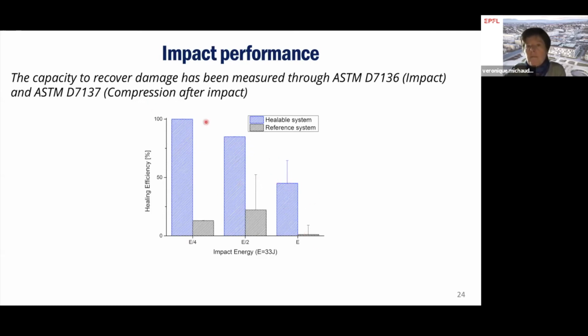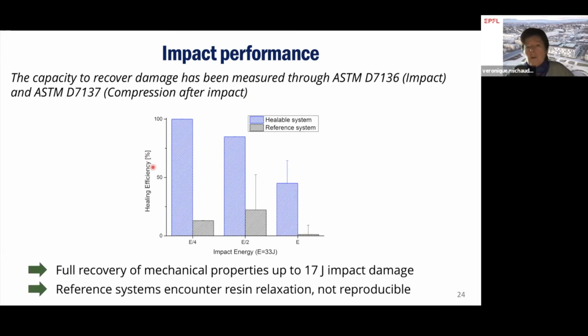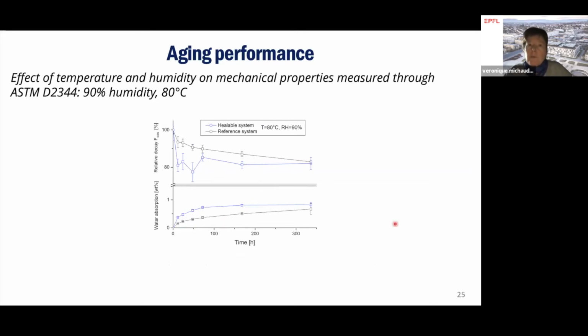And we see also that we have increased the resistance and the healability of our material compared to our initial blends, because we increased also the toughness, which makes the material less sensitive to damage after impact initially. So this was very interesting. And then if you have the pure resin only after heating at 150 degrees, the reference system, we see that we have a bit of healing due to resin relaxation, but it is not reproducible, with a very large variation in the properties.